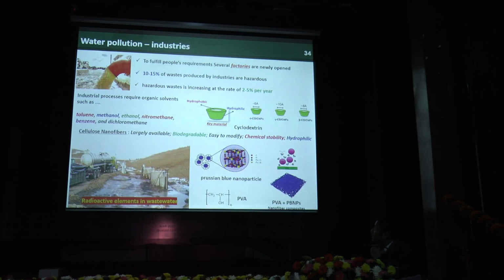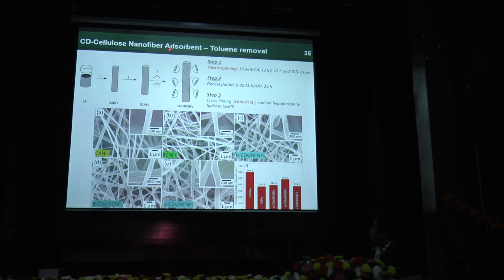So our environmental team developed some absorbent materials by using nanofibers. Cyclodextrin is one of the very good materials to remove organic solvents from industrial wastewater. So we modified the nanofiber with the cyclodextrin material. In the previous case, we coated nanoparticles for the catalytic application. In this case, we did covalent modification of the surface with cyclodextrin material. And as I said previously, even after modification, maintaining the structure is very important.